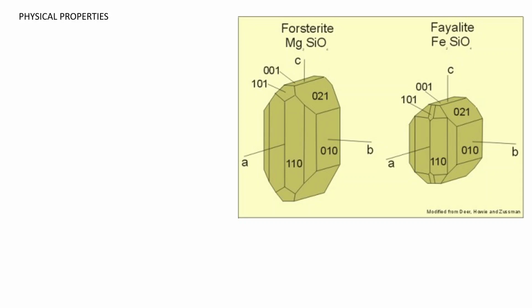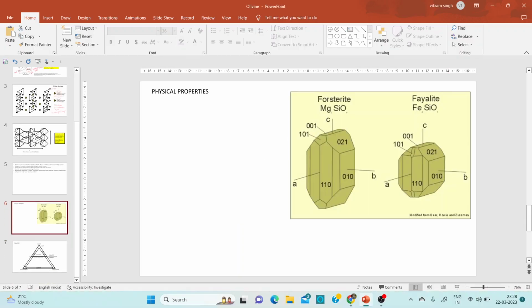So the first olivines to separate from a liquid of given composition are rich in Mg2+, and consequently the larger Fe2+ is rich in the residual melt. This is the reason for the higher abundance of forsterite than fayalite in natural systems. Let me add one slide here. As I have been discussing since the beginning, forsterite olivine forms first from the melt.